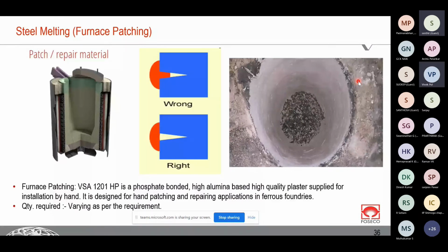During usage, there is always a tendency of some crack formation because of the thermal contraction and expansion behavior of the lining material. So how to take care of these cracks? That is what we tried to show you in this picture. Do not fill the cracks like this. We just need to apply the patching material just to cover the crack. Because when we start the furnace again and the material gets heated up, these cracks automatically close because of the thermal expansion property of the material.